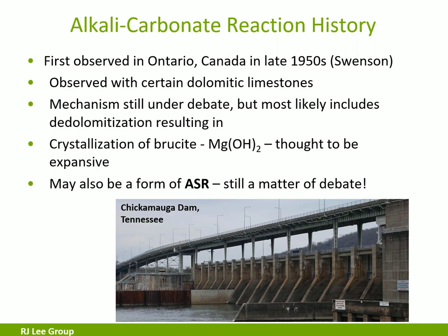testing. Damage shows up pretty quickly here, but there is stark debate in the research community whether the damage to structures is actually being caused by alkali carbonate reaction, or by alkali silica reaction, which is sometimes seen in correlation with damaged structures.